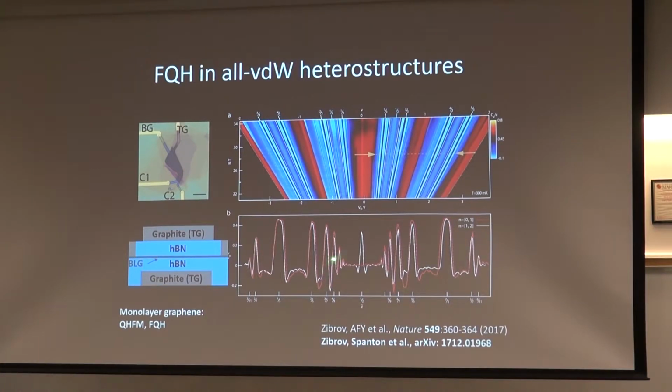So basically, we started, to give a brief history of this field, graphene started with graphene devices on silicon oxide. It turns out that they were relatively clean for something that you make with Scotch tape and very elementary e-beam lithography practices, but that the basic mechanism that limits ultimately the bandwidth of your Landau levels, but also all kinds of transport properties, is the fact that silicon oxide is an amorphous material. It has lots of charge traps, and this was sort of the leading problem. You got mobilities on the order of 10 or 20,000 at best if you were very careful in that type of geometry.